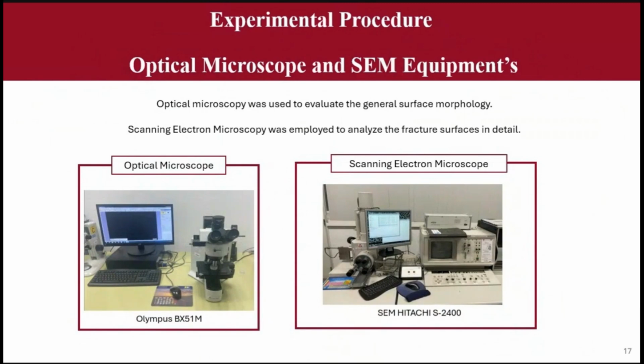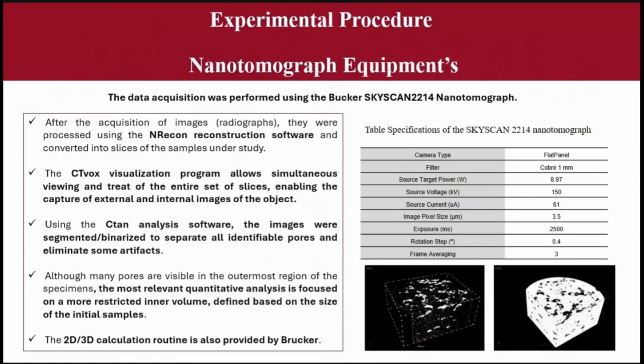For the manufacturing defects study, we use the optical microscope and the scanning electron microscope that are in the figures. The data acquisition for nanotomography was performed using the Bruker SkyScan, and this is also complex. After the acquisition, the radiographs were processed using NRecon reconstruction software and converted into slices of the samples under study.